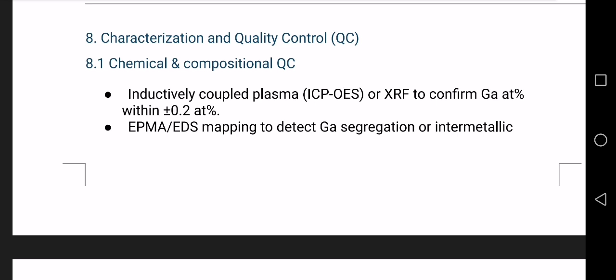Now that we have fabricated the material, we must verify its quality. We are going to verify the quality of the material. Chemical and compositional quality control. Composition verification methods are ICP-OES and XRF, and its purpose is to confirm gallium content within ±0.2 at%. This is critical because small composition changes strongly affect magnetostriction.